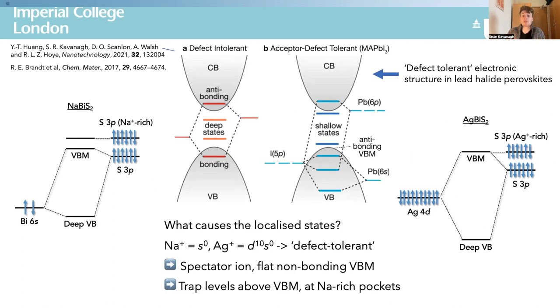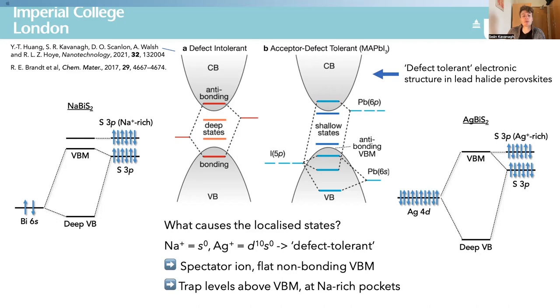This mechanism — where the electronic structure of silver bismuth sulfide makes it far more tolerant to localised states — is actually the same mechanism as one of the most accepted contributing factors to defect tolerance in perovskites. The same antibonding-type interaction at the valence band maximum increases the VBM energy, making localised states associated with defects become shallow in the band gap — pushing them closer to the band edge and thus making them benign with respect to trapping and recombination. Defect tolerance is essentially the magic behind perovskites, allowing them to achieve high efficiencies despite cheap solution growth. This serves as an important example of how the underlying orbital chemistry will dictate how disorder or defects affect the electronic properties of a material.